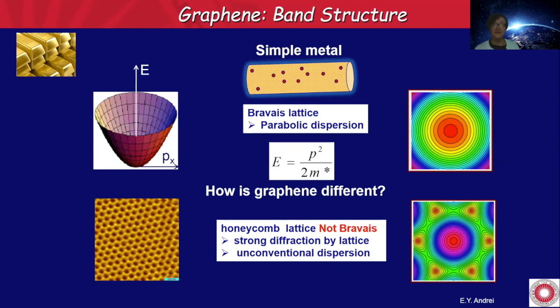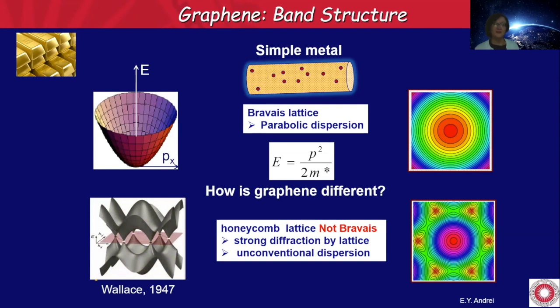However, in the case of graphene, because this is not a Bravais lattice, you get strong diffraction from the lattice, and the band structure looks nothing like this beautiful parabola. It actually looks like this. This was already solved back in 1947 by Wallace. And let's see what the consequences of such band structure are.